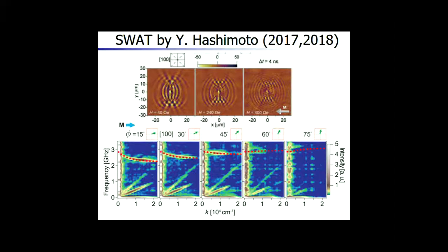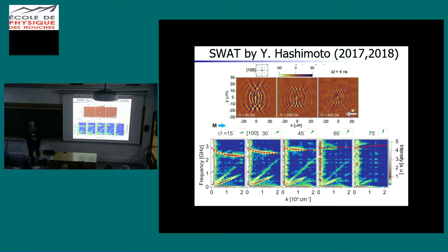Now this technique was then later developed further by Yusuke Hashimoto from the Saito group actually, and he saw much more fine structure in his experiments, as you see here, for example. The reason for that is that these YIG samples have a much lower damping than the previous ones by Ogawa. What he then does is he Fourier transforms everything from real space in time to reciprocal space in frequency, and he gets this nice dispersion relation in which he can really observe the dispersion of the phonons and the magnons, and he calls this SWAT, spin wave tomography.